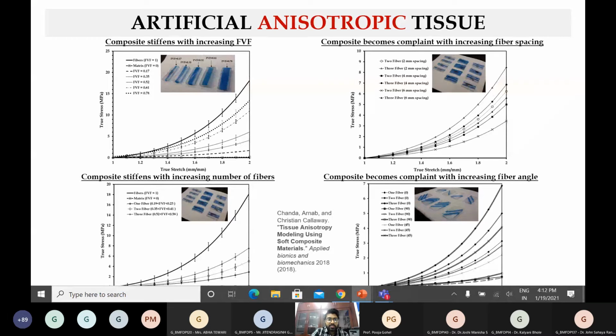So here are some of the specimens. What we controlled were 2-3 things. First, we increase the fiber volume fraction, the fiber amount. The inside blue part is much harder or stiffer, the outer part is much softer. The inside part we consider to be mimicking a fiber, the outside part a softer matrix. So we looked at different fiber volume fractions, how much of the entire soft composite is really fiber versus how much is the matrix.